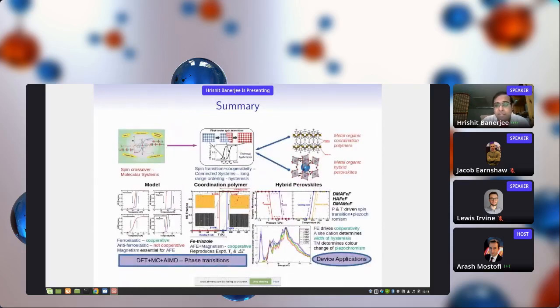And with that, just a minute left. Yeah. So with that, I would like to summarize. So in summary, we can go from spin crossover in molecular systems to spin transition and cooperativity in connected systems with long-range ordering and hysteresis. We show this in two different classes of materials. In the metal organic coordination polymers, we can show from our model that ferroelastic interactions are cooperative, whereas antiferroelastic are non-cooperative, and magnetism is essential for antiferroelastic interactions.